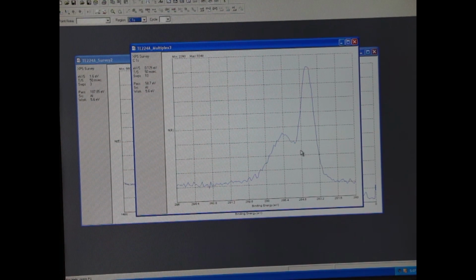And the important thing here is that for a given element, if we have it present in more than one oxidation state, we will get more than one peak. So in the case of carbon, for example, neutral carbon will hold on to its electrons with some intensity and therefore will give rise to electrons at a particular binding energy. If that carbon is oxidized in the form of a carbonyl group or a carboxylic acid, it will hold on to its electrons more tightly and it will increase the binding energy. So here we have a binding energy of 284 volts, and here we have a binding energy of 286 volts. So using that, we can determine what's the distribution of oxidation states within an element. Perhaps more importantly, by quantitatively determining the area under these peaks, we can determine the ratios of different elements.